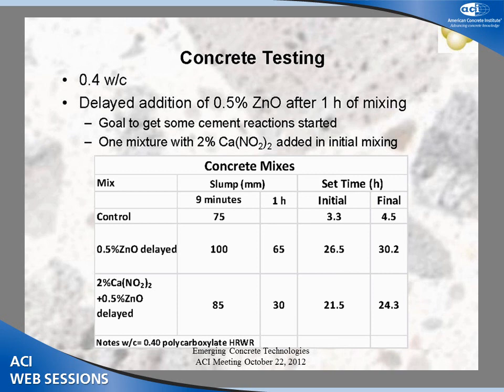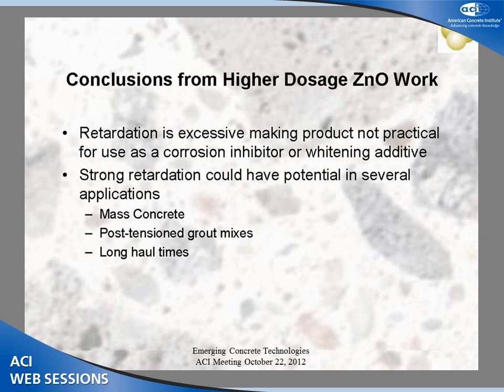In the case of the mix that had 2% calcium nitrite plus the delayed addition, 0.5% zinc oxide, the slump was 85 millimeters after 9 minutes, and it was down to a little bit over 1 inch, 30 millimeters after 1 hour. But again, the most powerful story that comes away from this work is, if you look on the right, you can see both the time to initial set and the time to final set was very, very long retardation. And it's not necessarily a bad thing, as I will explain.